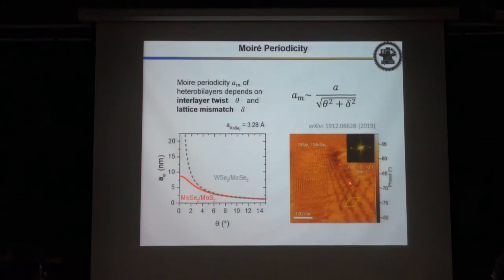So you can see there can form some irregular Moiré pattern, because if you do mechanical stacking and you have some structure defects, you will form this kind of thing. So this area is very regular, but here it becomes irregular. So it is not easy to keep this kind of long range, large periodicity. It's especially hard for optical measurement, because the optical beam size is at micron scale. So if you want to study how the periodicity affects the electronic behavior, you had better use a lattice mismatch system like this.